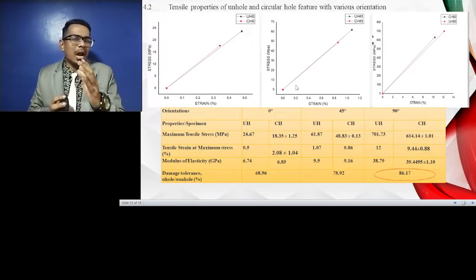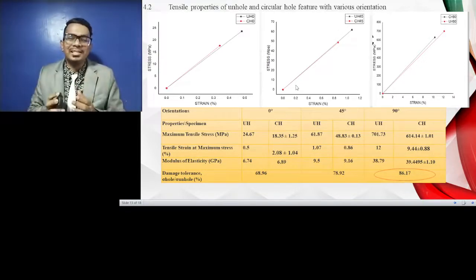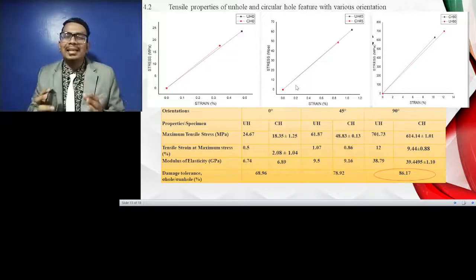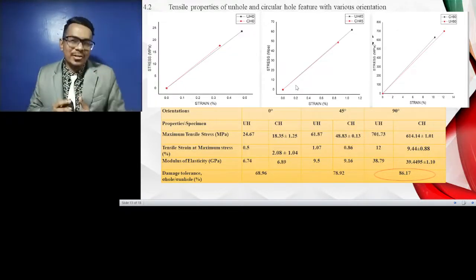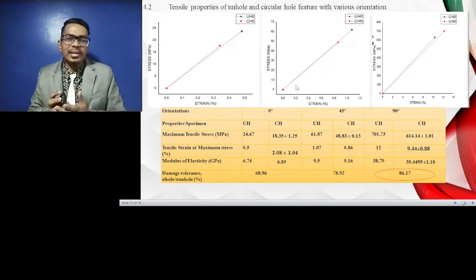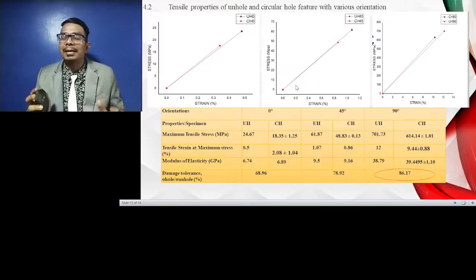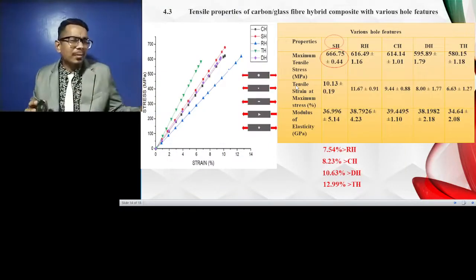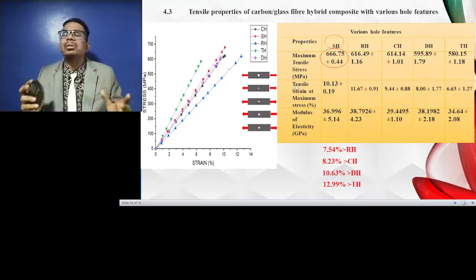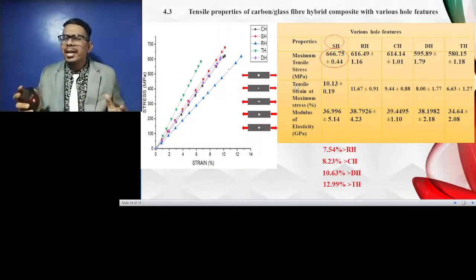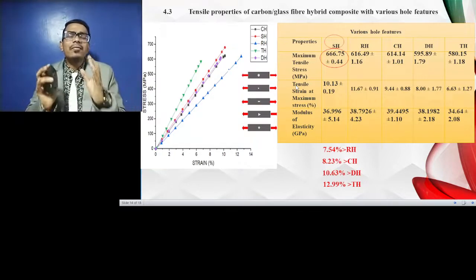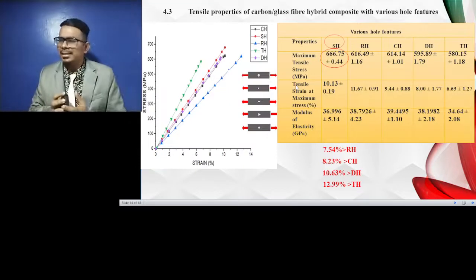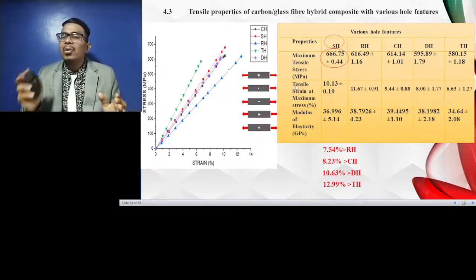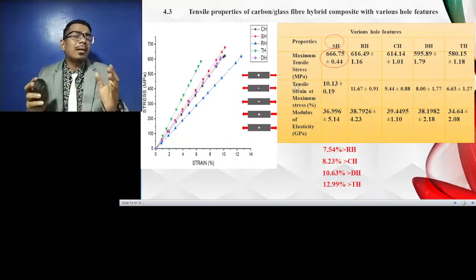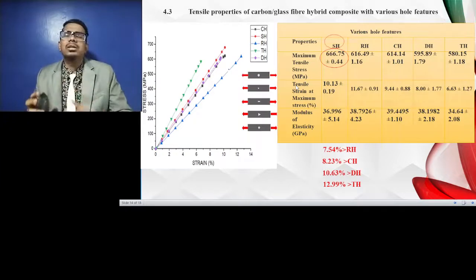Subsequently, the tensile properties of the unholed and circular hole features with various orientations are discussed in this part. Obviously, it shows that the hole in the specimens affects the tensile result. From this table, we can see that the 90-degree orientation recorded the highest values in all categories, but the 0-degree orientation recorded the lowest results in all categories. Followed by that, it was observed that the square hole specimens recorded the higher tensile strength, while the triangular holes recorded the lowest. This is because surface stress concentration is higher at the sharp edges compared to the square cross-section. The triangle cross-section has sharper edges, which means a higher chance of failure. Thus, it breaks too fast and recorded the lowest tensile strength.